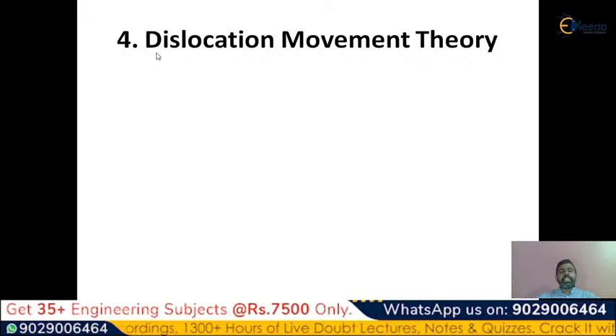The next one is the dislocation movement theory. This is a very understandable and important theory which explains the failure mechanism. In any material, if the dislocations are not restricted, I repeat, if the dislocation movement is not restricted, you cannot avoid the fatigue failure or the creep failure or whatever failures are observed in the material. You cannot avoid the cracks observed in the material.